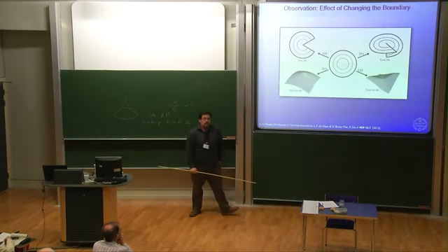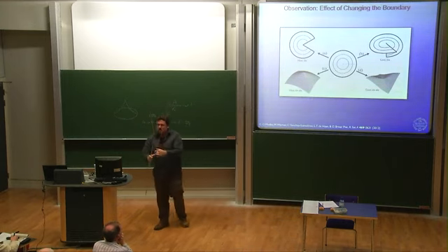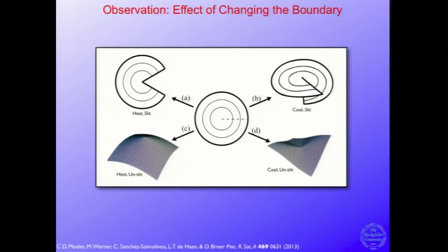You take an azimuthal +1 disk and you cut a radius out of it, and then you heat it. That radius just opens up, the thing stays in plane. The radius opens up and you get sort of a Pac-Man shape. And if you cool it, that radius buckles out of plane enough to slide over itself, and you get sort of an envelope closing.